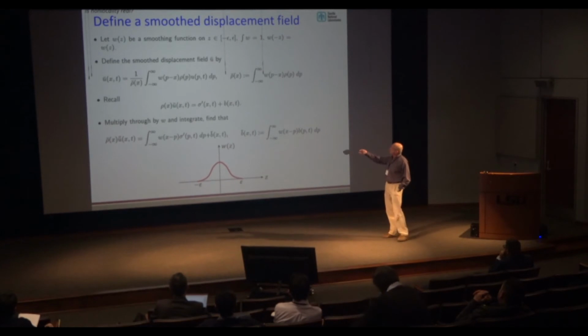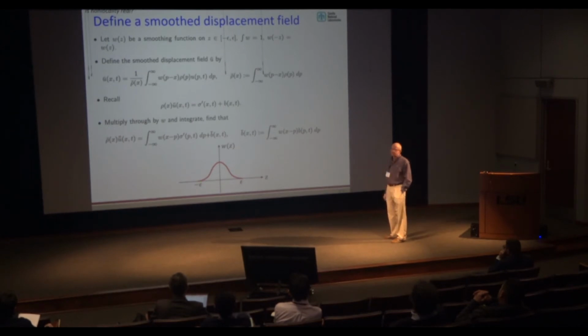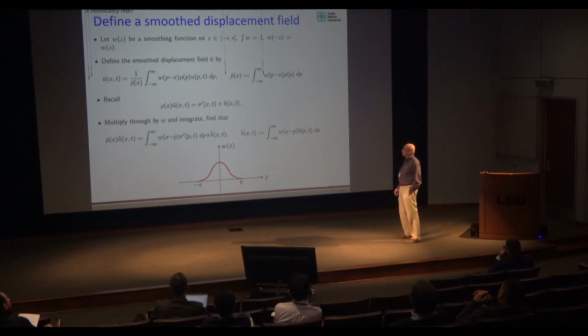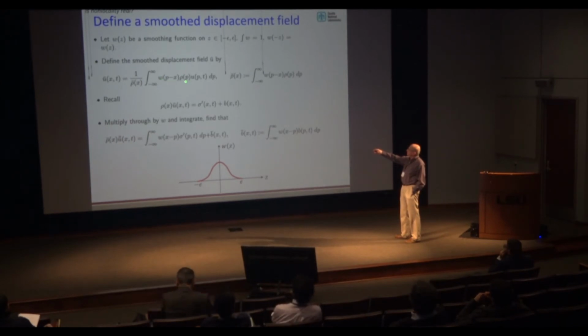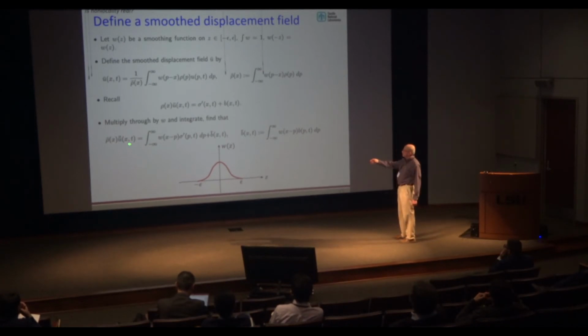So we'll apply a smoothing function that looks sort of like this, sort of Gaussian looking thing, to the displacements in that bar. And we don't know what those are yet. So we'll define the smoothed degrees of freedom by applying this smoothing function over an integral weighted by the density to the small scale displacements. And we'll also define the smoothed density by this equation. So then we'll take the local PDE, multiply it by the smoothing function, and integrate, and we end up with this result, which gives the acceleration of the smooth degrees of freedom, and it involves this integral. Then what?